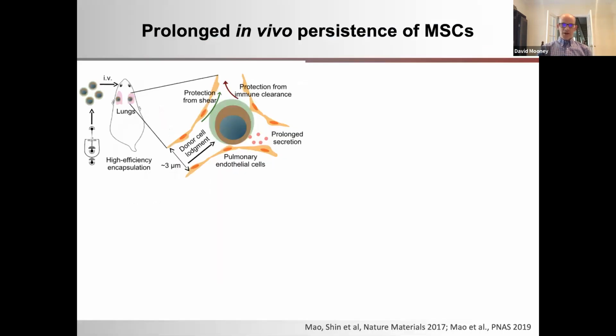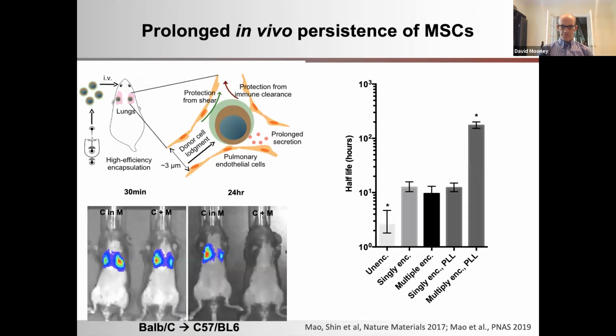By doing this, we can control the behavior of the cells, and importantly, we can control their persistence. So for example, if we do an intravenous infusion of these cells, the majority of them will be trapped in the lungs, which is what always happens with this mode of delivery. But the premise is that the hydrogel coating could protect the cells from the mechanical environment and from being cleared by immune systems, and prolong their ability to secrete therapeutic agents into the body. And indeed, when we take these cells and encapsulate them and follow the fluorescent signal from the cells, you see immediately following injection, cells that are in microgels and cells that are outside of microgels both largely lodge in the lungs.